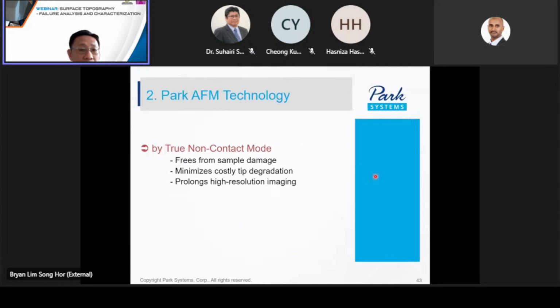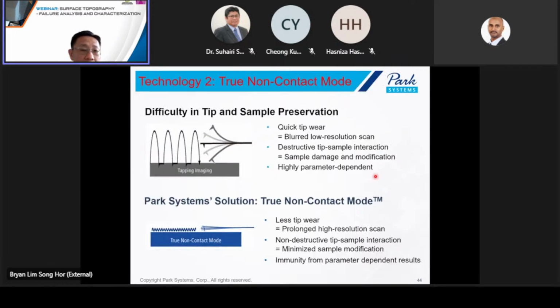So another technology which I'm going to talk about is this non-contact mode, right? Non-contact mode means the tip is barely touching the surface. As a result of this non-contact mode, the tip degradation is very low, and it prolongs the tip lifetime. Okay, so this is tapping mode. The tip is tapping on the surface. However, this will cause the tip to be blunted very fast. So for Park Systems, we have this true non-contact mode where the tip is oscillating and measuring the surface, but it is not really touching the surface. So as a result, your tip can last for many scans.